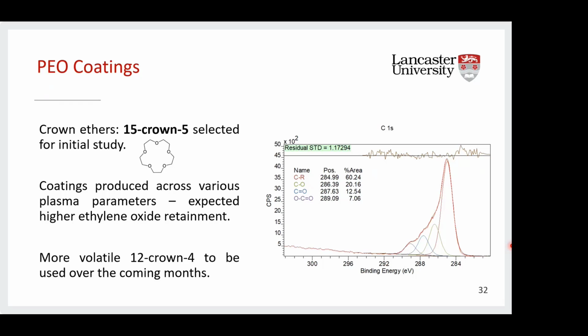Initially, we began with deposition methods similar to those we used with ethanol, so we were using a high pressure, low power regime. But what we found was this monomer is very temperamental. It's quite viscous, so it's very challenging to actually vaporize in the first instance. And even in the coatings that we did produce, we're not maximizing the ethylene oxide character in the way we'd want to. So this hydrocarbon peak is clearly dominating the spectra.